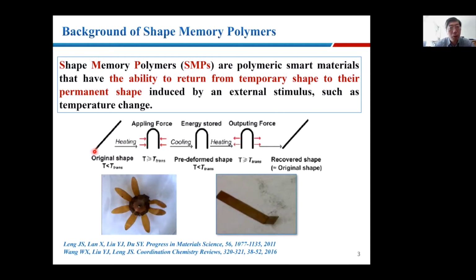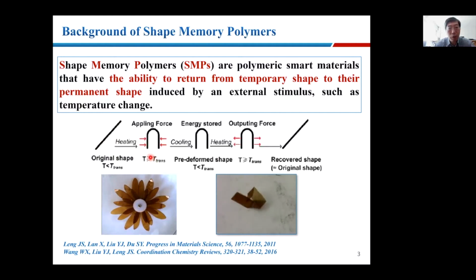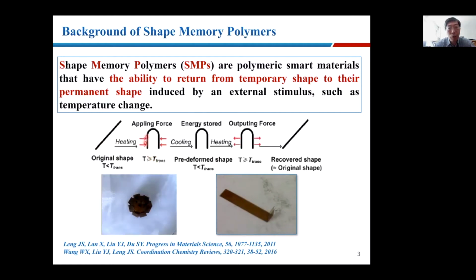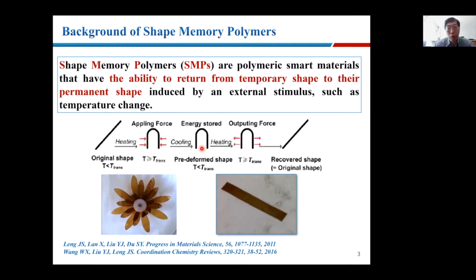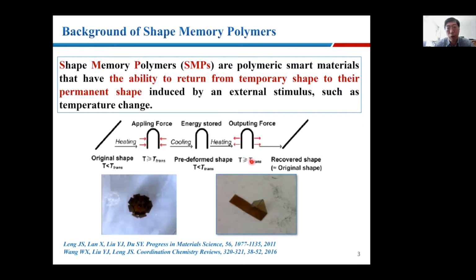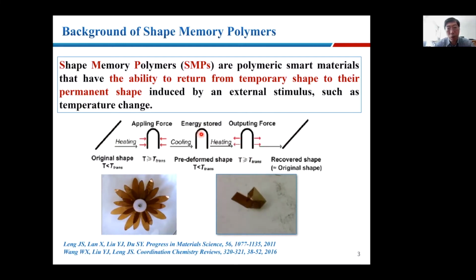So for shape memory polymer, if you have an original shape like this one, when you're heating above the Tg, above the transition temperature, the material can become very soft like elastomer. So that means you can apply force to force the polymer to any shape you like. When you're cooling down below the Tg, the material can keep the shape, which means energy can be stored. So whenever you need, you just simply heat above the Tg. Then the material can recover to the original shape, which is this one. So you have the original shape, you have the pre-deformed, which is the temporary shape, and you have the recovery shape, like this one.